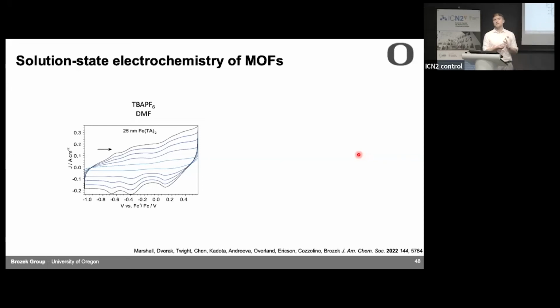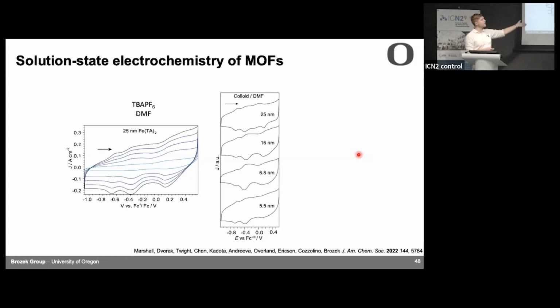That's really weird. Because think about it, the difference between ferrocenium and decamethylferrocenium is about half a volt. And that's one of the best examples of how you can tune a redox couple of something. Here, this should all be the same iron chemistry. The environment should be the same, and they're differing by almost a volt. So something weird is happening here. So we thought, is this an impurity? These were the 25 nanometer particles. We tried this on all the different sizes, and we see something really similar, multiple fairly reversible waves. So what's going on here?